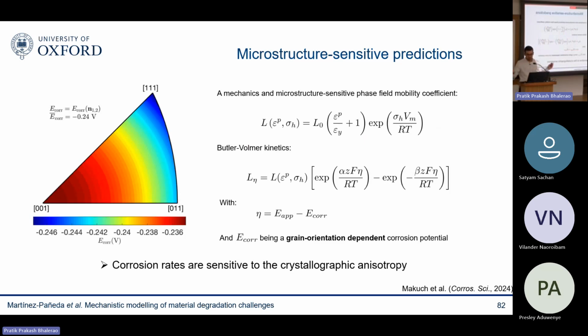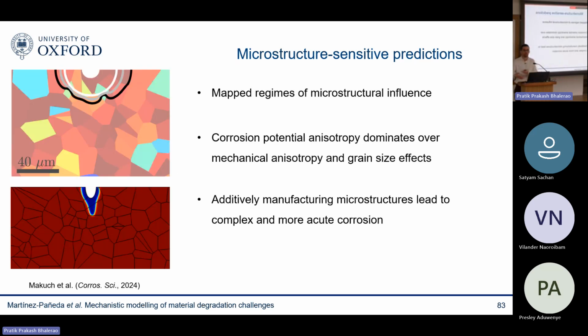The microstructure also plays a role. We know that there's not only the mechanical crystalline anisotropy, but also there's corrosion rate anisotropy. So we can define a grain orientation dependent corrosion potential, and then we can do simulations and basically compare with the isotropic case and understand under which cases we need to resolve the microstructure, creating maps like this one, but also understanding what happens with 3D printing materials where you have different microstructures. Are they more or less resistant to corrosion? How does the resulting microstructure play a role in those cases?